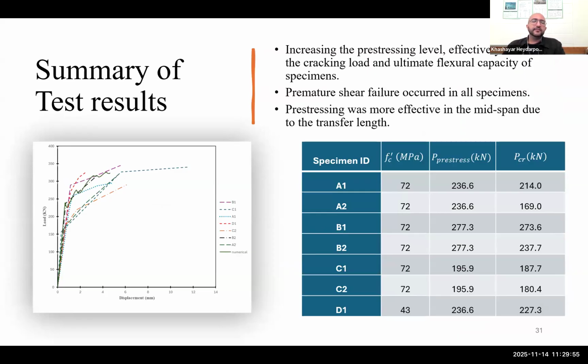At the end, we can summarize the tests like this, that increasing the pre-stressing level effectively increased the cracking load and ultimate flexural capacity of specimens. And we can also say that premature shear failure occurred in all specimens, and pre-stressing was also more effective in the midspan due to the transfer length.